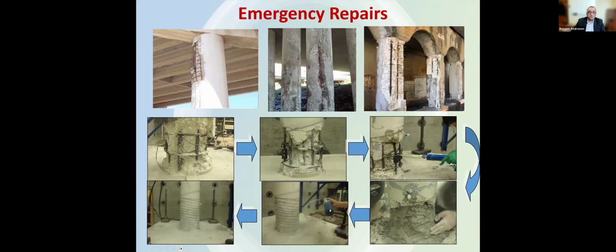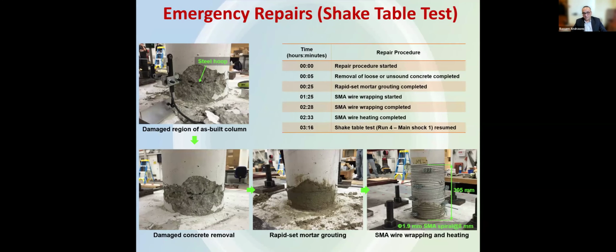And you see here my former student just applying, with a blowtorch, just heating it. In a matter of seconds, you see the spiral, even before your own eyes, attempting to squeeze the column and apply the confining pressure. So we wanted to test this concept under actual dynamic load effect. And the best way to do this is through a shake table test. That's actually the only way to do it right now in our labs.